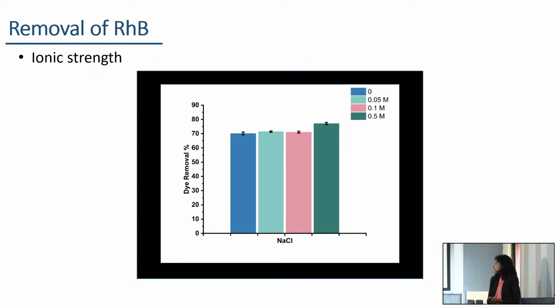The reason is the overall charge of this composite is positive, as measured using the zeta potential values. During this adsorption process at high salt concentrations, the negatively charged chloride ions can screen the positive charge of this composite, reducing the repulsion interactions between positively charged rhodamine B dye molecules and the positively charged GO-based composite. Eventually, this will increase the rhodamine B adsorption onto the GO-based composite through hydrogen bond interactions.